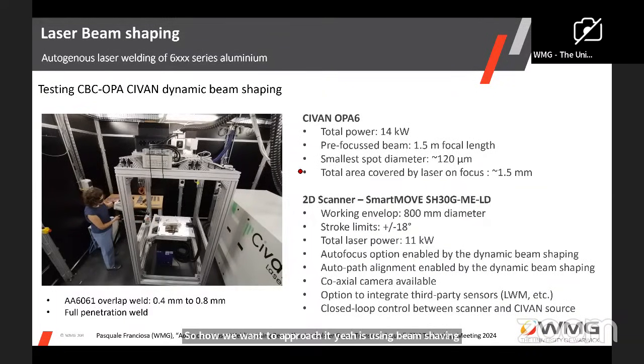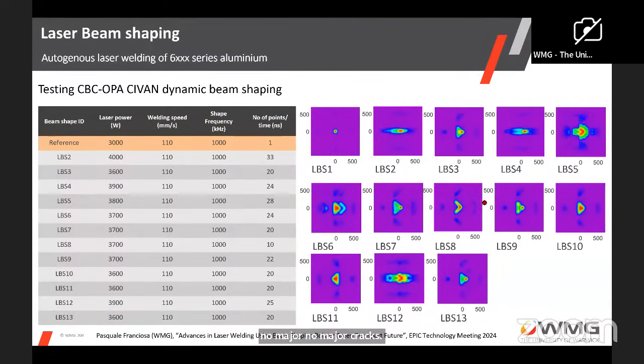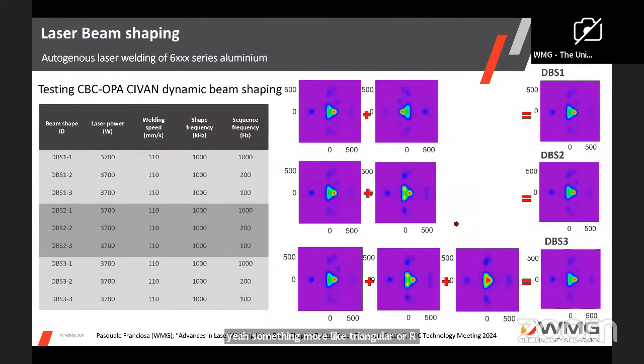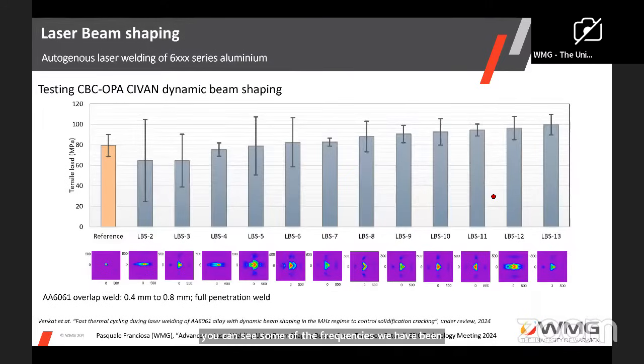So we have been testing over the last few months the technology from CBC, so the coherent beam combiner with optical phased array. Now, without going into the technical details of the setup, in essence, it is 14 kilowatts total, although for the materials we have been using, we have used far below, around 3 kilowatts. So it's a combination of 0.4 to 0.8 millimeter 6061 aluminum in overlap. The requirement is a full penetration weld and obviously structural, so no major cracks. So we tested different shapes. This is one set, starting from a standard single core to something more like a triangular or arrow-based shape. And then we also tested something more dynamic. And you can see some of the frequencies we have been using. And those are some of the results now.